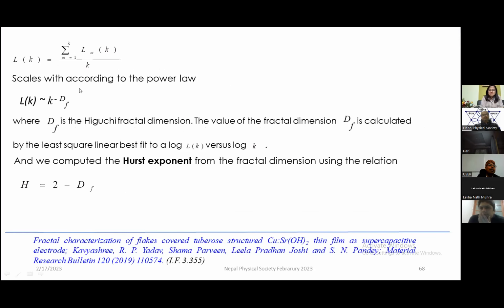Basically we get Lk proportional to k raised to the power minus df, where df is the Higuchi fractal dimension. This is the fractal dimension that one can obtain. Once the fractal dimension is obtained, we can calculate the Hurst exponent. The Hurst exponent H is equal to 2 minus df. The fractal dimension df is not always an integer; it can have any value. So 2 minus df gives you H, which shows that H and df are opposite to each other.